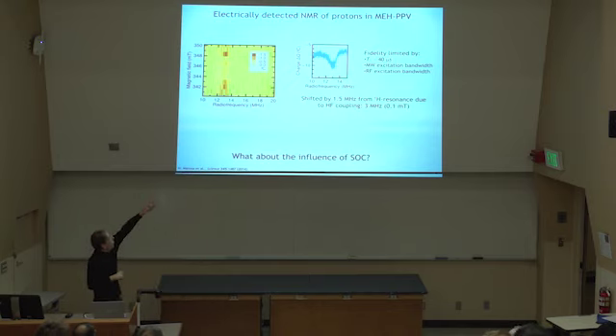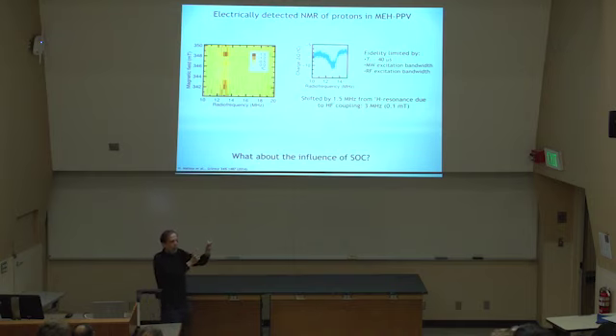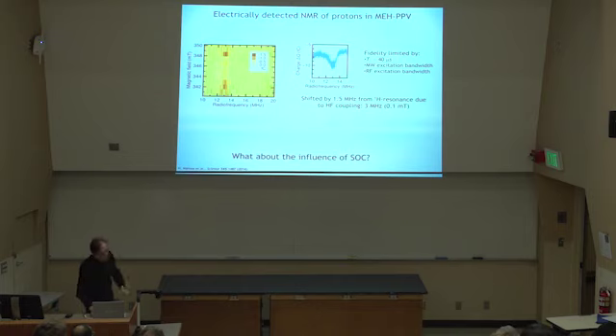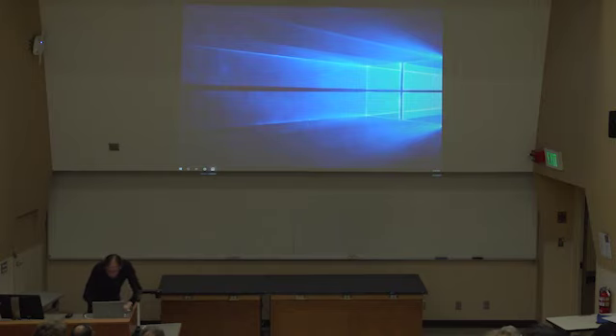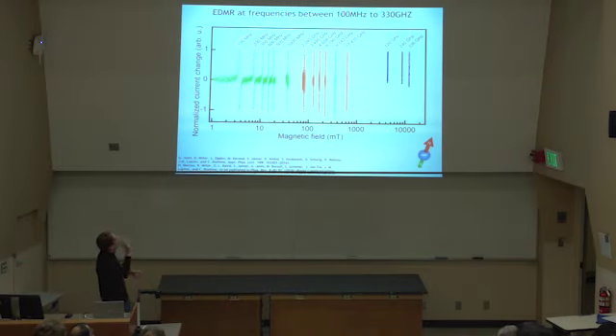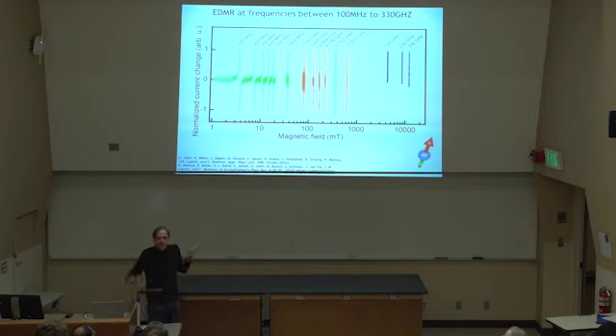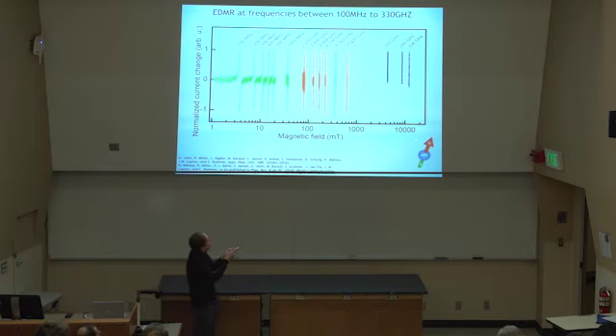So far, most of what I've done here, these electrically detected magnetic resonance manipulations, was done at an excitation frequency around 10 gigahertz, at magnetic fields of about 350 millitesla. That's what all of this has been. Now we repeat this in a magnetic field range of, let me show that, somewhere between 1 millitesla. And yes, we can detect magnetic resonance at 1 millitesla, as I've explained earlier, all the way to about 10 Tesla. Actually, 12 Tesla was our highest magnetic field that we've applied.